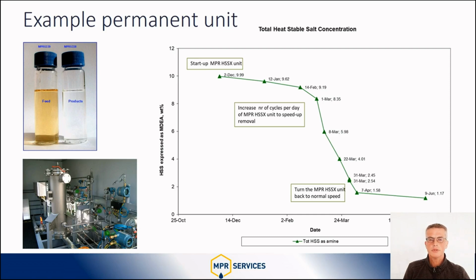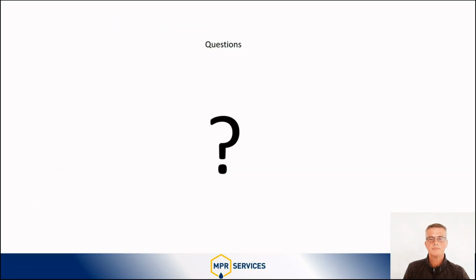The permanent unit brought down the heat stable salts, as you can see in the graph. It reduced the levels of formate and gave back the amine and activator that was earlier tied up. The iron and the iron cyanide levels went down to less than 10 ppm. But most important was that syngas capacity could be increased.